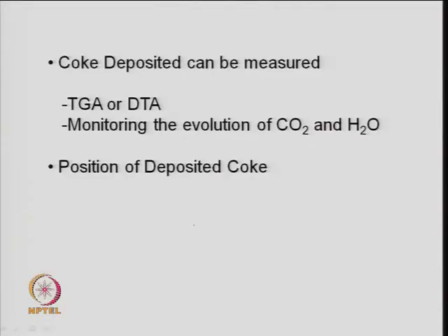One can measure the amount of carbon deposited as a function of time and at different temperatures. How much coke is removed when you burn it in TGA, one can find out, and then you can correlate it, or you can understand the mechanism of coke formation also. This coking mechanism itself is a complex phenomenon.